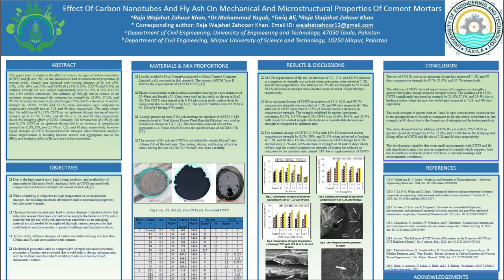In this study we reinforced mortar cubes with fly ash and carbon nanotubes at different percentages. For fly ash, we replaced cement at 5, 10, 15, and 20 percent. Similarly, we replaced cement with different dosages of carbon nanotubes from 0.125 to 0.5 percent — as a total volume replacement of cement. Apart from that, the optimum dosage of fly ash was independently combined with different dosages of carbon nanotubes.